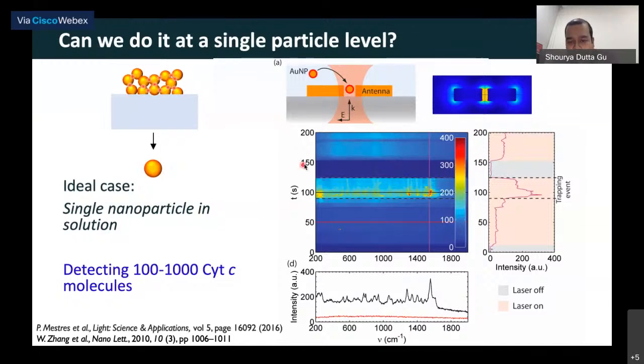And then if you turn it on again, we don't see the particle anymore, right? So what this tells us is here there was no particle between 0 and let's say around 100. Between 100 and 120 in seconds in time, we have the particle being trapped and we can measure the Raman. And then again, we release the particle. So this is a typical example of plasmonic tweezers.